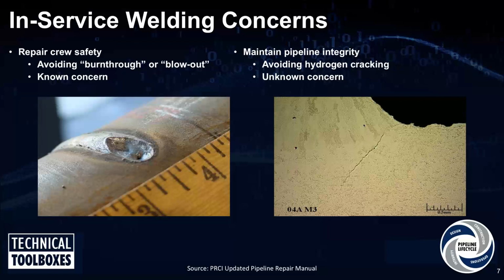So the burn through concern really goes back to the safety of the welding crew. When a burn through occurs, you put a hole in the pipe and the product comes out of the pipeline, it can be quite dangerous. That being said, I'm not aware of many instances where a burn through has actually resulted in, say, a fire. It has occurred a couple of times, but it's not as common as someone might expect. But it is a real concern, obviously, to the welders. Hydrogen cracking, that really goes to the integrity of the pipeline. When you're making welds, obviously you don't want any welds to crack. But hydrogen cracking tends to be more of a concern for in-service welds.